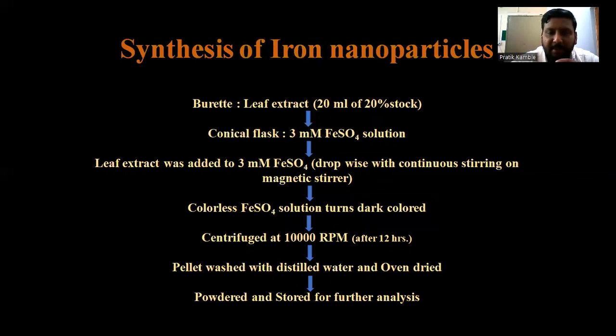Synthesis of iron nanoparticles. We have followed the standard protocol for the synthesis of iron nanoparticles biologically. In a burette, 20 ml of 20% leaf extract stock was taken. In a conical flask, 3 millimolar FeSO4 solution was taken. Then leaf extract was added to the 3 millimolar FeSO4 solution dropwise with continuous stirring on a magnetic stirrer. Colorless FeSO4 solution turns dark colored. It indicates the formation of iron nanoparticles.